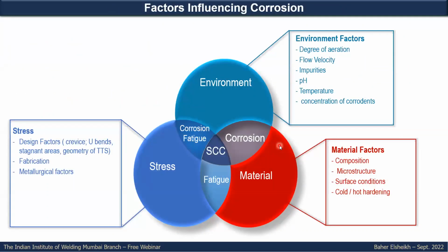As a general thinking, corrosion might happen by the combination of environment, material, and stress. Environment, stress, and the material together, if the condition can be applied, are the three required factors for stress corrosion cracking. With environment and stress only, you might have corrosion fatigue. Material with a susceptible environment, you might have corrosion, and the material with stresses, you might have fatigue.